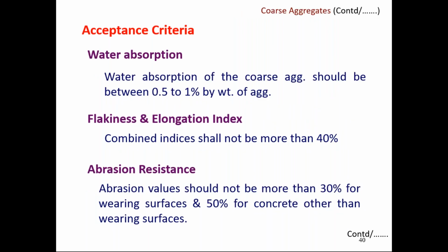Water absorption is another important property of both coarse and fine aggregates. For coarse aggregate, water absorption will normally start from a very low value of 0.2, 0.3, about 0.5% to 1%. And for fine aggregates, it will be up to 2%.